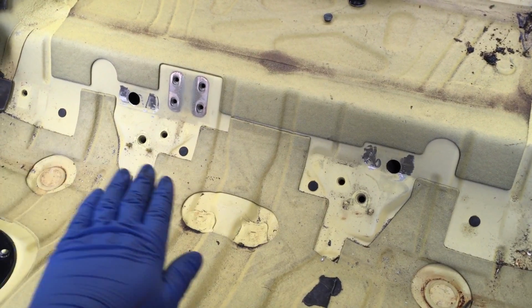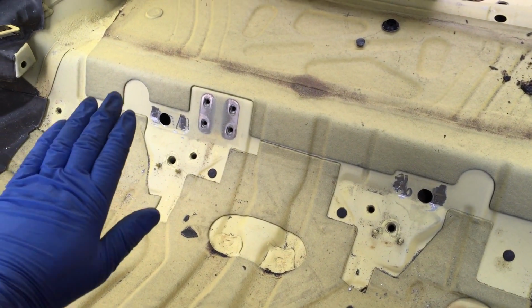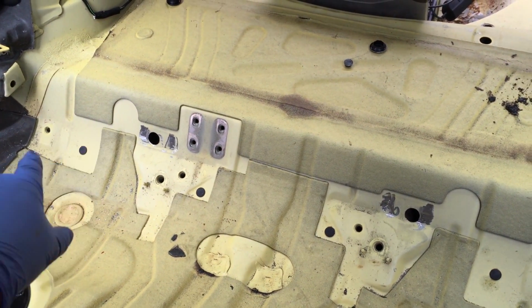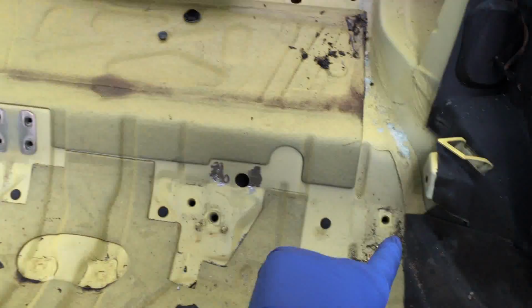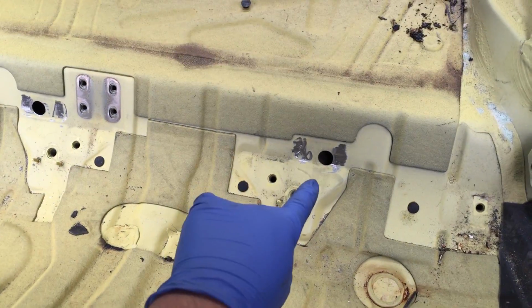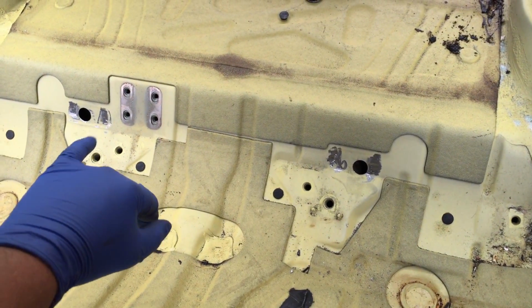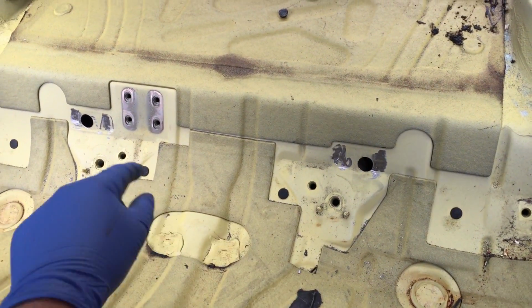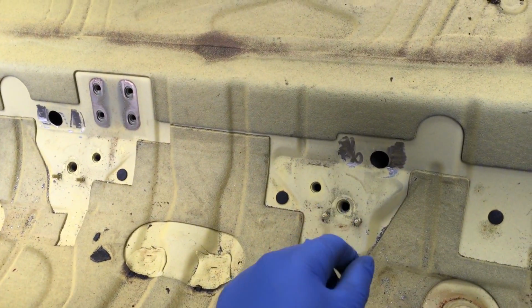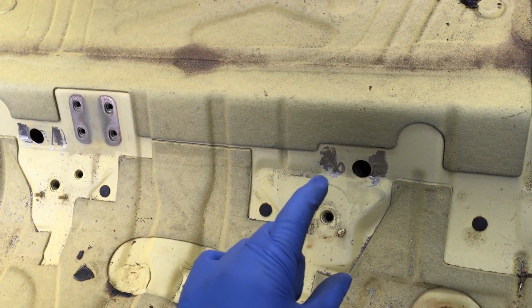We're now on the back seat area here. This is the seat panel. This is quite a flimsy panel, 0.75mm thin, which sometimes suffers with spot weld breakage down the side. And we've taken off a pair of redundant brackets that aren't used on these models, drilled a 20mm access hole to look at the cavity mounts, the 2 MIG welded points that are holding the front threaded mounts in for the rear subframe panel.